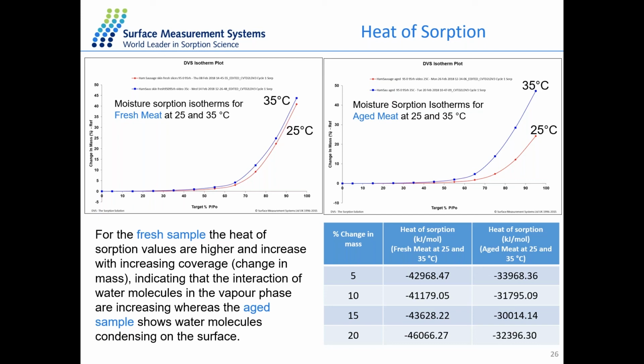The aged meat sample is the same sample after 1 week in the fridge, and the fresh sample shows very similar results, almost overlapping at the 2 different temperatures. For the aged meat sample, it shows quite a large difference in uptake at 35 degrees compared to 25 degrees. So from the isotherm, we can calculate the heat of sorption with our macros. It's summarized in the table here. So the heat of sorption is much higher with the fresh meat sample compared to the aged meat sample.